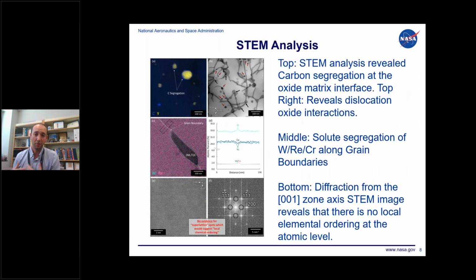We were able to take that powder, successfully print it, and start doing some characterization of the microstructure. Some notable things we found: we do see carbon segregation at the interface between the oxide and the metal matrix. We aren't sure if that has any additional benefit to the properties, but it was an interesting observation we could see with high resolution TEM analysis.